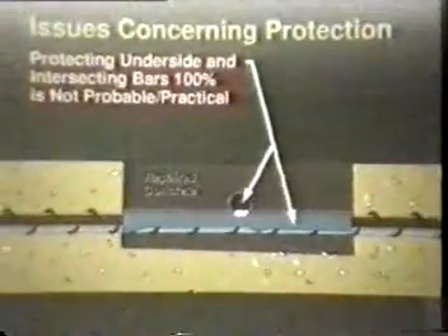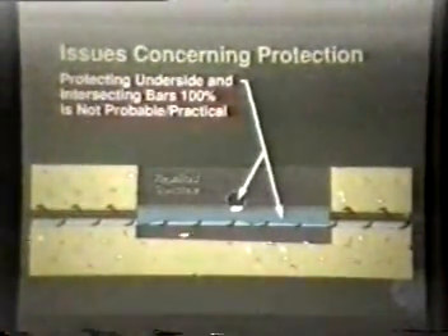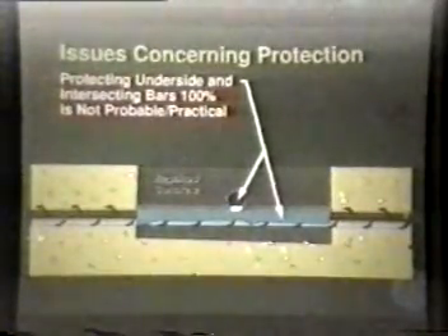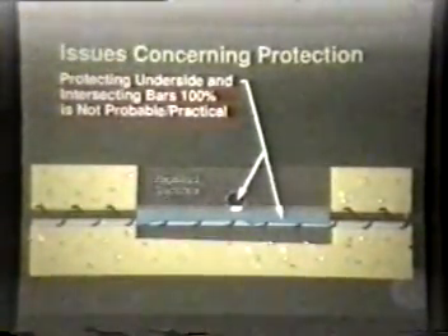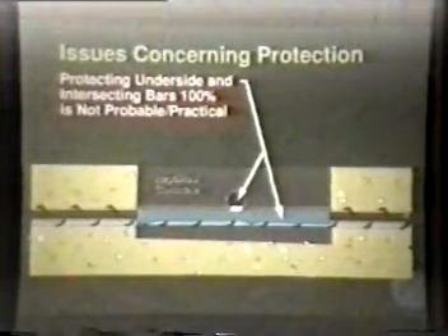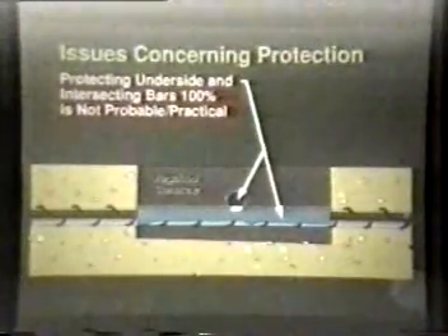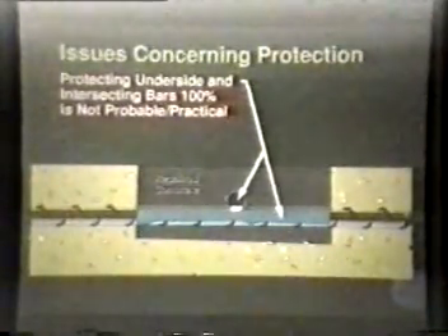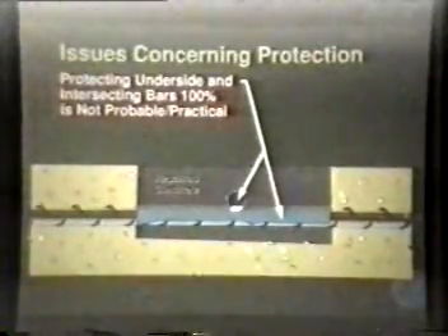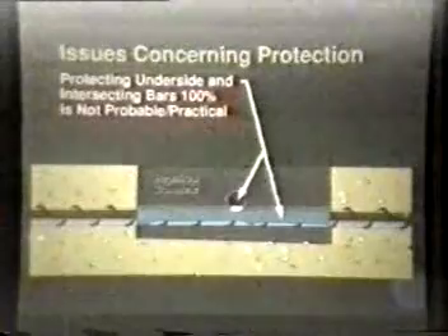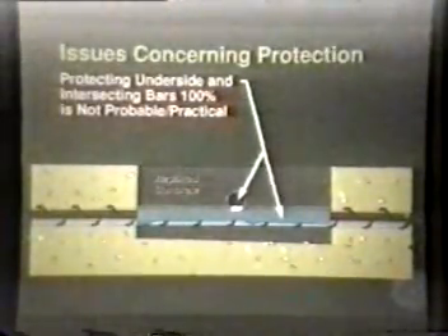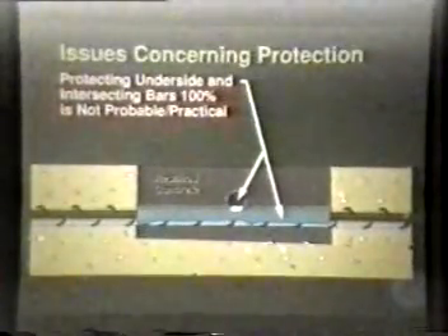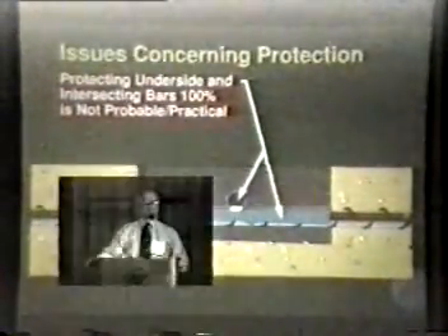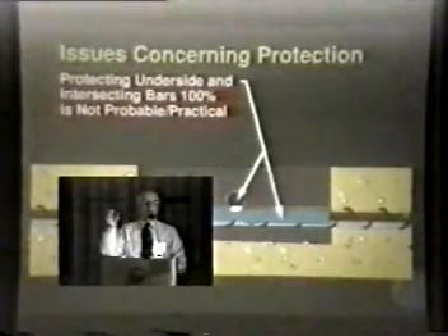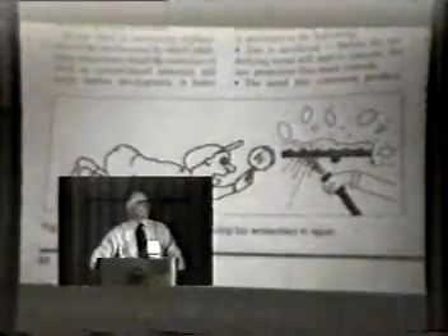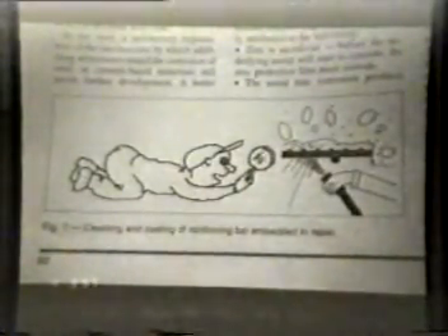And then we deal with the constructability of that. How do you coat, I'm talking about epoxy coating now, where epoxy coating is an electrical insulator, and for electrical insulators to work, they have to be perfect. If you have a pinhole in it, you concentrate electrical currents. So an engineer that specifies this wants a pinhole-free, perfect coating system. But as a contractor, I can tell you it's very difficult to do this. On the back side of the bars, it's very difficult. Where bars intersect, you have two number 8 bars lapping each other. You know how difficult that is? It's almost impossible. They're touching. There's going to be a gap there, uncoated. So it really brings into question the issue of the practicality of it.